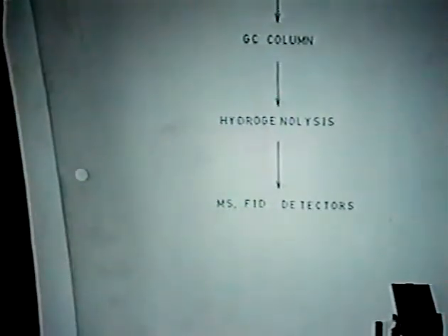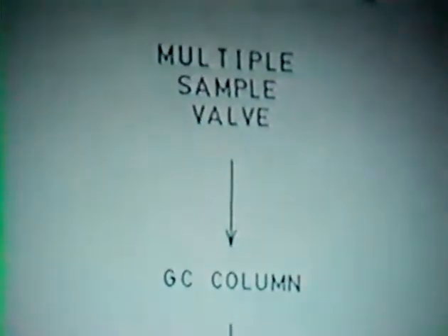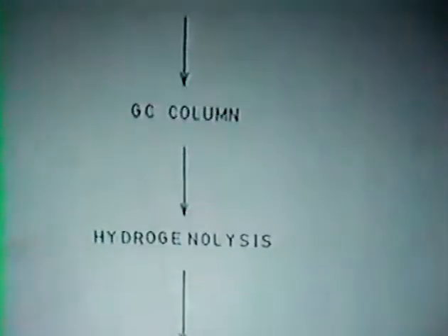This experiment is similar to one we saw this morning. We're doing it in a slightly different way. We have a multiple sample valve, and we do our switch from carbon-12 CO hydrogen to carbon-13 CO hydrogen, and then we have 16 loops, and we turn the valve every few seconds and trap a sample, and then analyze afterwards. And afterwards the whole transient experiment is done. We send these in a hydrogen carrier gas.